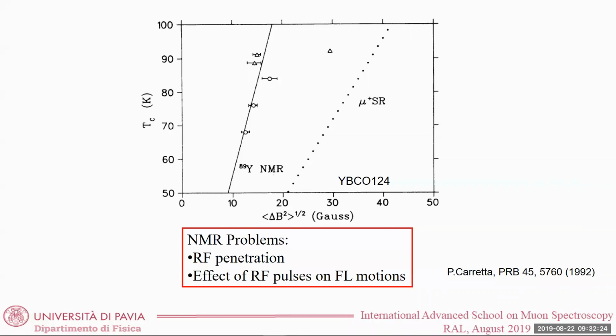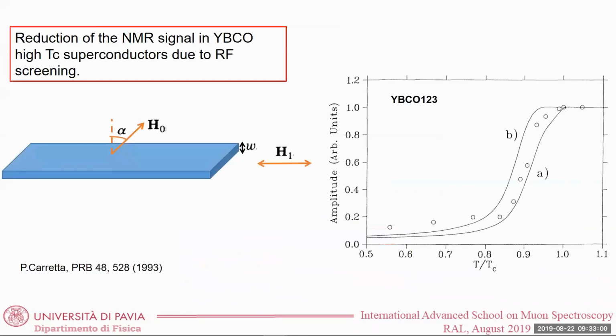The other point which I would make is that when you do NMR, of course, you have to apply radio frequency pulses to perturb the system and study the time evolution of the nuclear magnetization. And when you apply radio frequency pulses, if your flux lines have a certain mobility, what you do is shake your flux lines, okay? And so your radio frequency pulse can induce a certain mobility of the flux line lattice and induce a non-negligible perturbation.